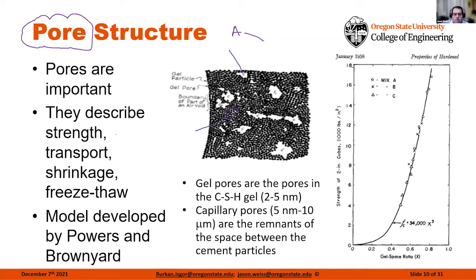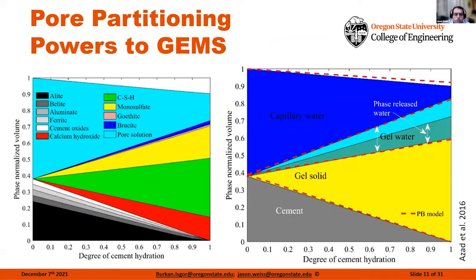And once you know the porosity, and once you know how these pores are distributed, you can start to predict things like strength, transport, shrinkage, and freeze thaw. And this is exactly what we're doing. So what we're doing here is we're taking the Gibbs energy minimization, the thermodynamic modeling. We're saying we have cementitious phases shown here in gray and white. We have the water shown here in aqua, and we predict the reacted products from calcium hydroxide to CSH to monosulfate. And then we actually map those over into a pore space type of a diagram. Now, what I've shown here in this pore space diagram is kind of the classic approach that people have used for cements.